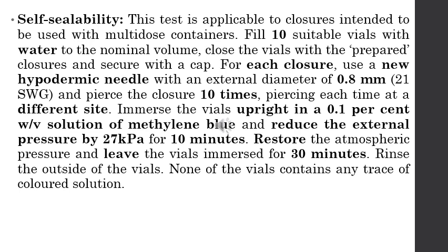That is 10 times at different places. After this, we have to immerse the vials upright in 0.1% weight by volume solution of methylene blue. Now methylene blue is blue in color. So we have to keep the vials in upright position in 0.1% methylene solution.